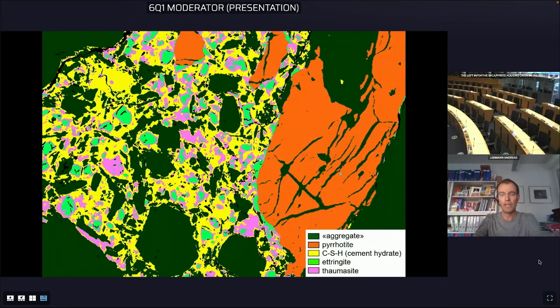Now, the legend is in your lower right corner. Dark green is the aggregate, bright orange the pyrrhotite, then yellow is the CSH that gives the concrete its strength. Green is ettringite. And very important here, you don't see monosulfate anymore because all the monosulfate has already been transferred to ettringite. This means this concrete has already gone through an expansion phase.